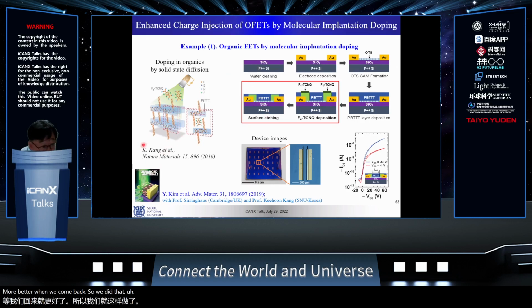So we did that. One of my postdocs, who got his degree from Cambridge and is now faculty at Seoul National University, did evaporation molecular doping on molecular or organic polymers in Cambridge. He evaporated so-called F4-TCNQ, which is not a mixing solution, so the evaporated molecule stays in a local area. From what they published, he got the idea to deposit F4-TCNQ only on the contact area. This enhances the charge injection, so charge injection current improved, mobility is better, and there are many good signs. One weakness of this approach is that although we deposit on the contact area, it is still a molecule, so it diffuses a little bit into the channel.